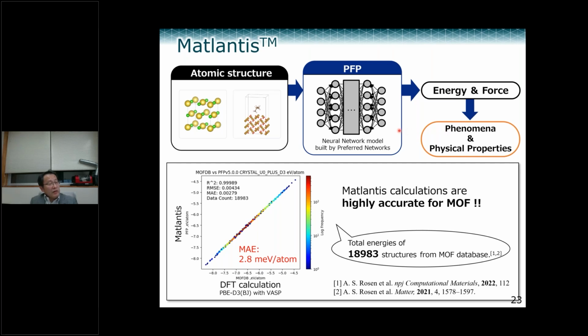This slide shows very important data about Matlantis. This graph shows a correlation between DFT calculation and Matlantis. Using a MOF database, okay, this is important. This plot comes from all MOF structures in the MOF database, almost 19,000 structures, a huge number of MOF structures.